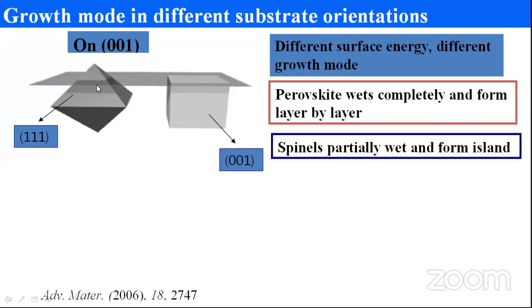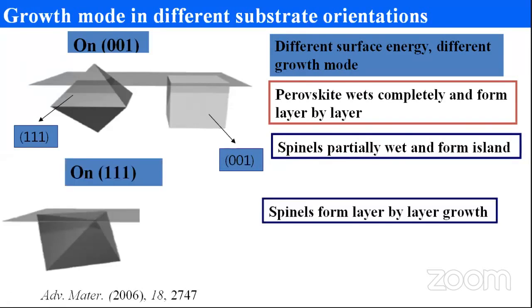Okay, so this is the reason why on a single substrate, your spinel will grow as a rod, and your perovskite will grow as a matrix layer by layer. On the other hand, if you change the substrate to 111 orientation, the spinel will wet completely, as I said in the previous slide. The surface energy is different for spinels on the 111 plane. So the spinel will wet completely.